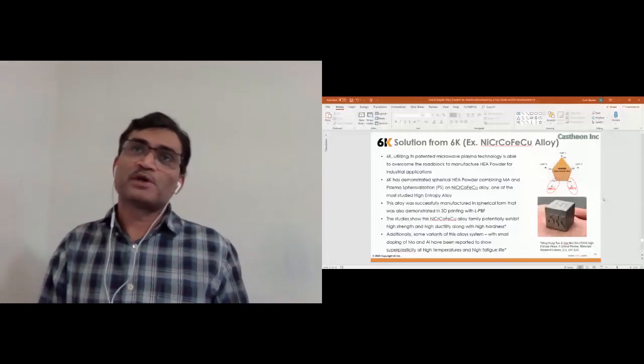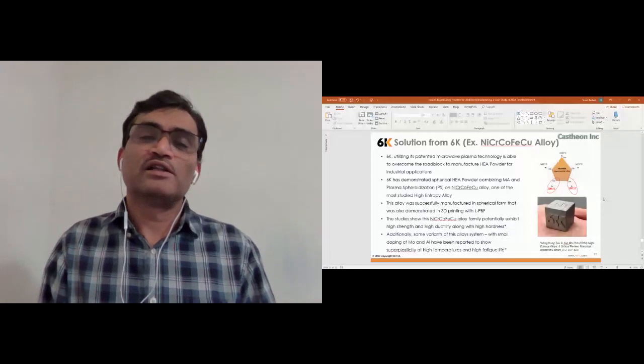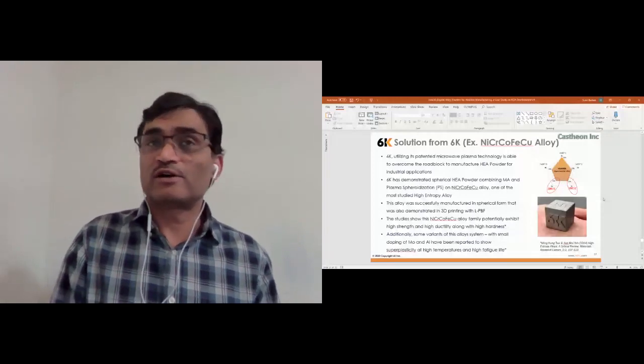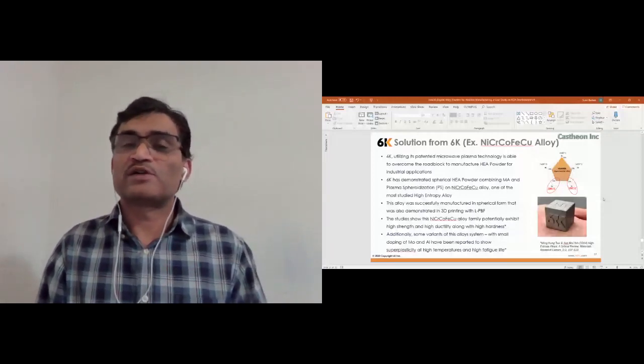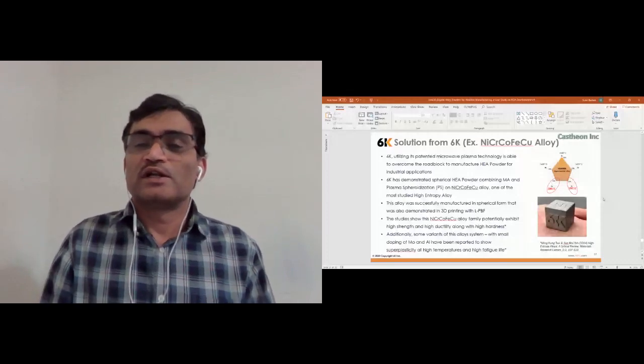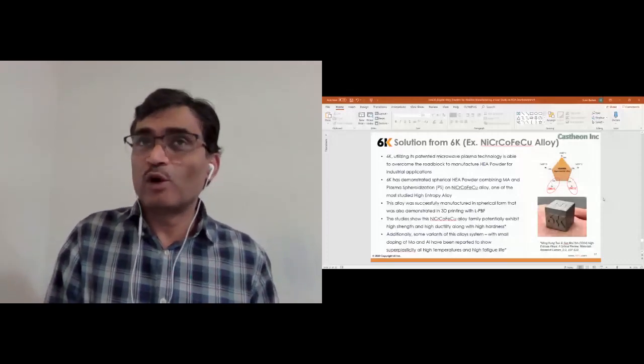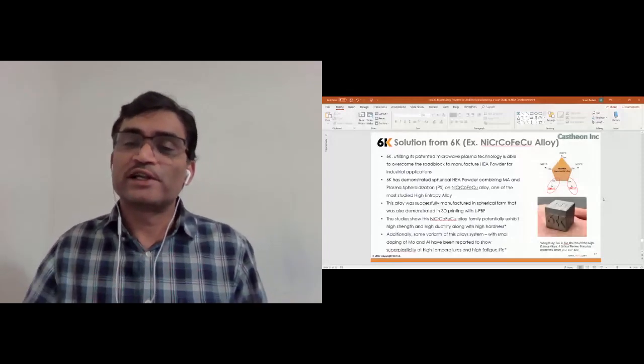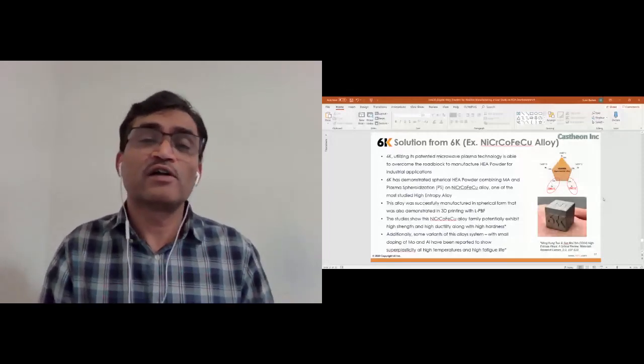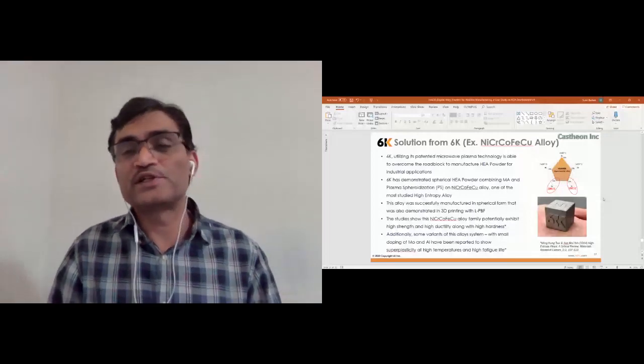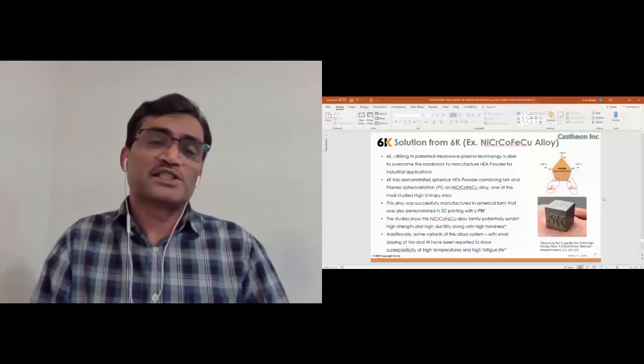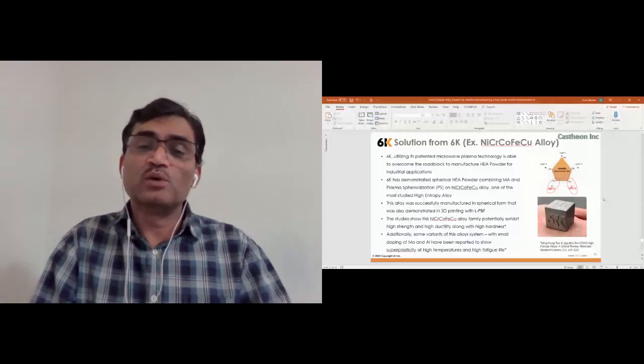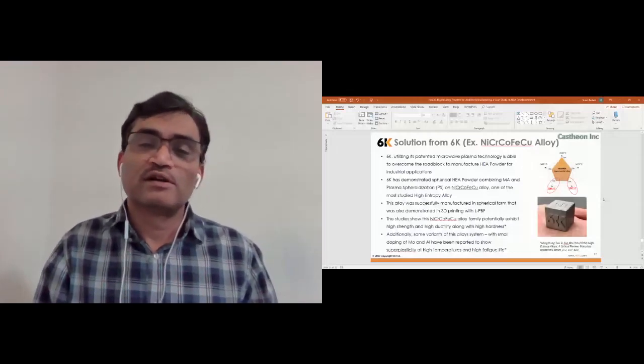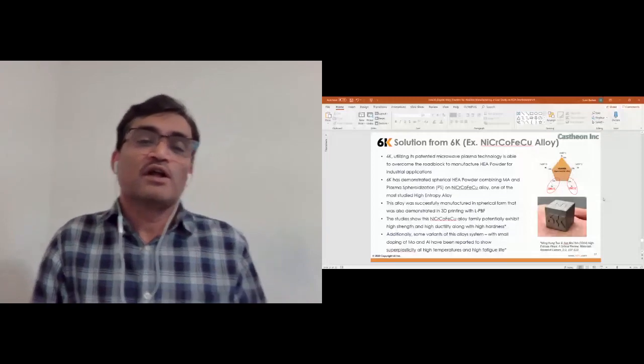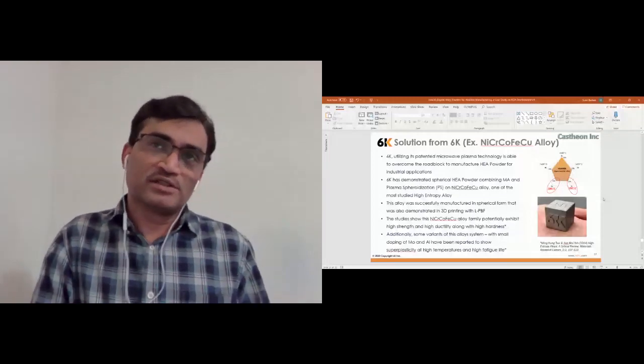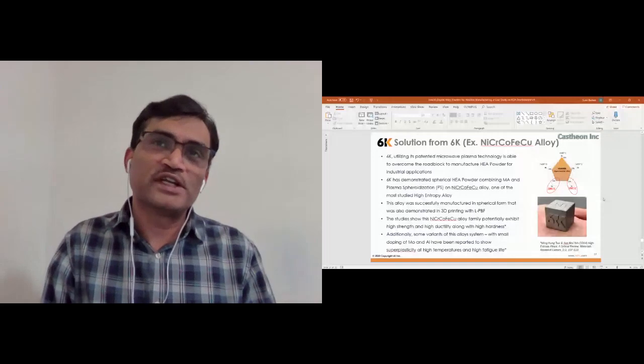For example, we have demonstrated one of the alloys. We have taken nickel, chromium, cobalt, iron, and copper alloy, where we have chosen copper because it has a very low melting temperature compared to the highest melting temperature element, chromium. It's like a 900 degrees C difference in melting temperature. So if we want to melt this kind of alloy, we will lose some of the alloying elements while we are trying to melt the other ones. And we chose this alloy based on the literature, which is one of the most studied alloys